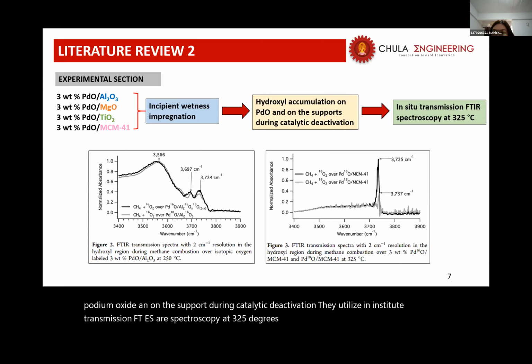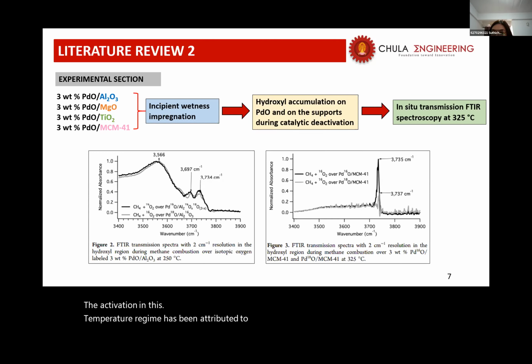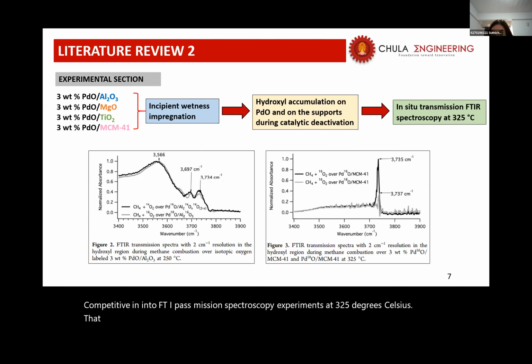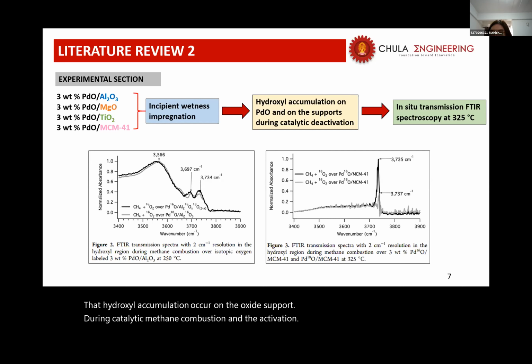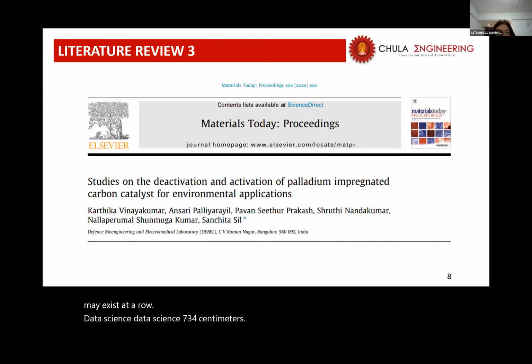325 degrees Celsius. Catalytic deactivation in this temperature regime has been attributed to a water or hydroxyl inhibition effect. Comparative in situ FTIR transmission spectroscopy experiments at 325 degrees Celsius reveal that hydroxyl accumulation occurs on the oxide support during catalytic methane combustion and deactivation. Hydroxyl accumulation on the catalyst also hinders the catalytic combustion reaction by blocking active catalytic sites. A palladium hydroxide bond may exist at around 3,734 centimeters inverse.